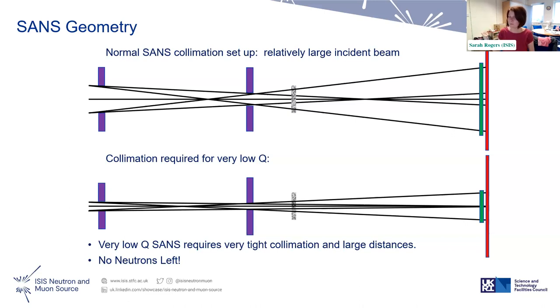So if you want to go to very low Q, i.e. look at very big stuff with traditional SANS geometry such as this, the way you get that spot on the detector to be as small as possible is to push the detectors further away. So that's why we go to these long detector distances to get to low Q. Which sounds great in principle, apart from the fact the more you push the detectors back, the lower the flux of the beam that comes to you. So it's always this balancing act between low Q and flux.